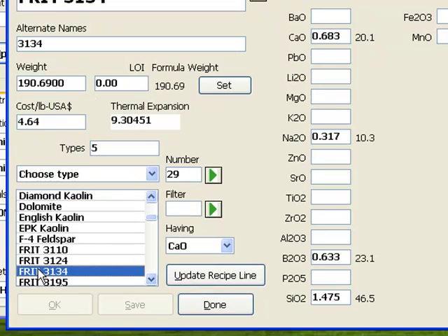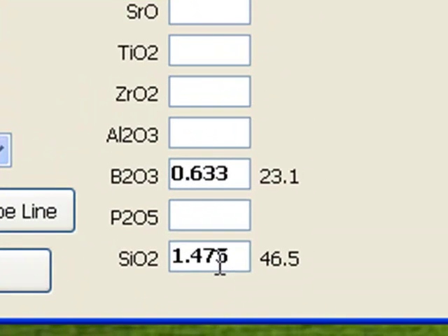Here's a boron frit. Notice that it has 20% CaO. If your glaze also needs sodium, boron, and silica, and the vast majority of glazes do, a frit like this is a good source of CaO. INSIGHT is a great way to figure out how to juggle things to incorporate frits into glaze recipes while maintaining the chemistry. The really great thing about this material is that no feldspar on Earth can offer this, no alumina. That makes more room in the recipe for clays. They are sources of alumina, and they suspend the slurry and harden the dried layer. In addition, frits generate no gases on firing.